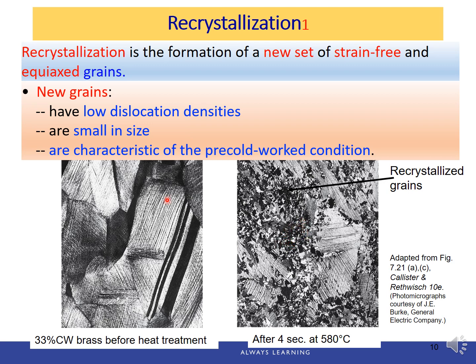So here is the microstructure of the grains during recrystallization. This is the brass before heat treatment, after 33% of cold work. So you can see the grain sizes are big. And after 4 seconds of heat treatment at the given temperature, which is 580, we can see those recrystallized grains. Those grains are much smaller than the original grain size. And also, those grains do not just grow on the old grain, but actually replace the old grain. So it consumes the parent grain and becomes smaller grains.